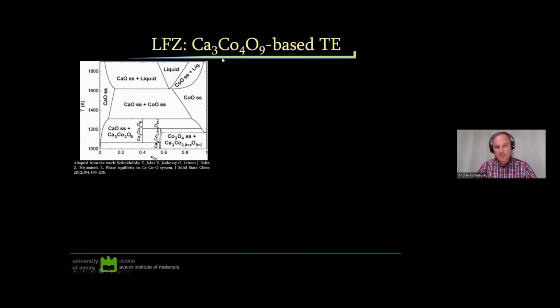Here is the example of the so-called 349 phase calcium cobaltite, which is a well-established thermoelectric oxide with interesting properties, a P-type material. So I can expect that by growing this material, we will basically freeze this high temperature condition, which corresponds to the mixture of calcium oxide and cobalt oxide. And this is what indeed happens.